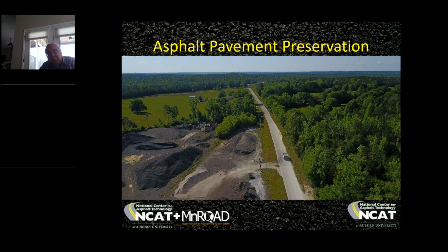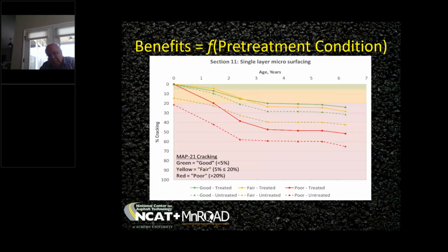This is a dead end access road to the asphalt plant and to a quarry located adjacent to the asphalt plant. As you can see on this road, we've put all different kinds of treatments. We put thin lays and microsurface and chip seals and cape seals and fog sealing and crack sealing and different combinations of those things, so that we can compare the rate at which distresses come back compared to what condition these sections were in before we placed them, and we can begin to develop life cycle curves for these treatments.